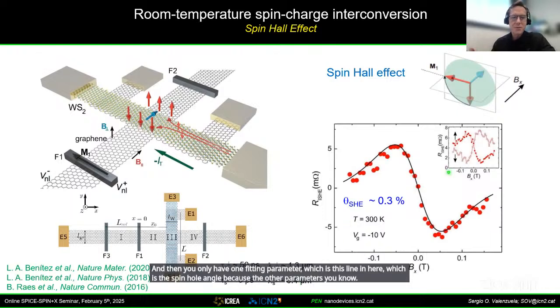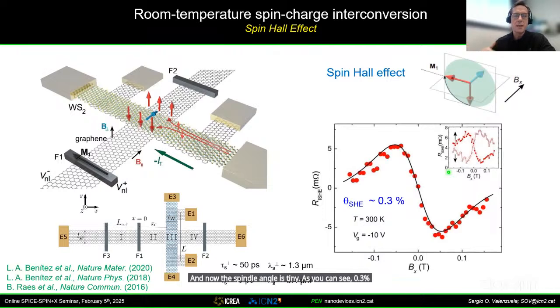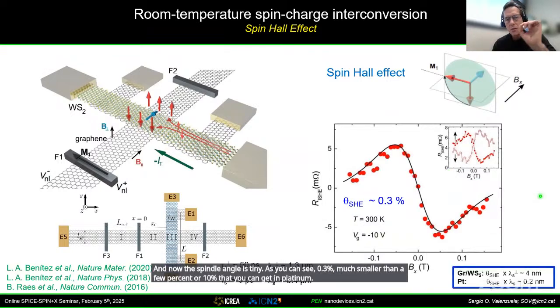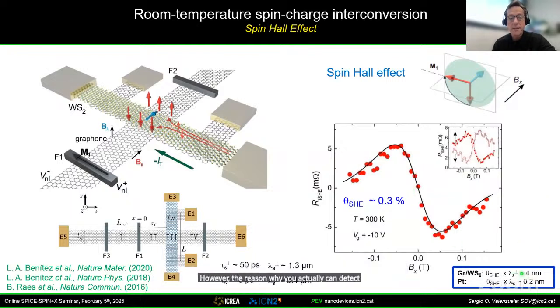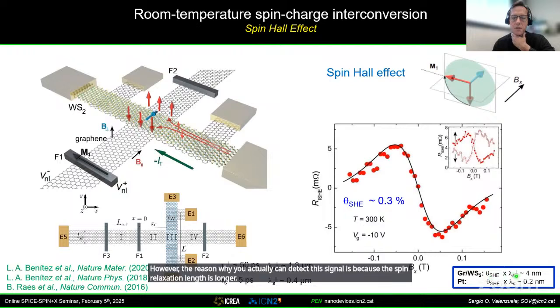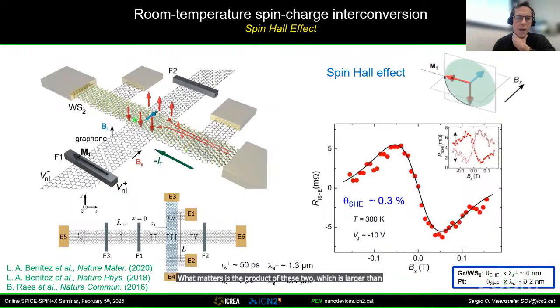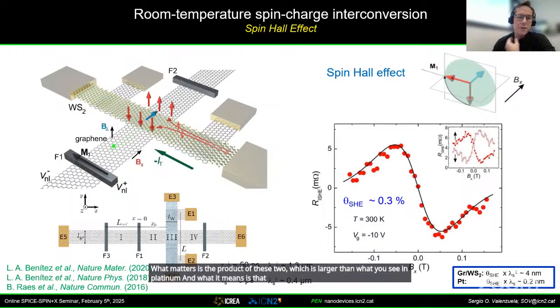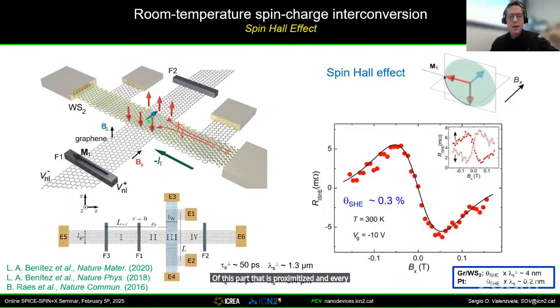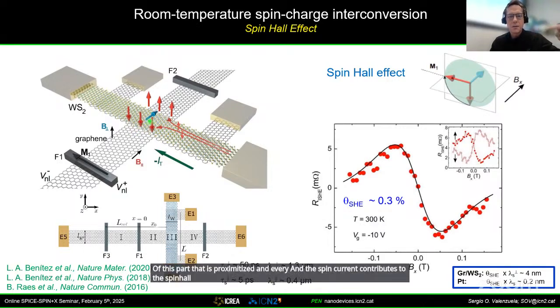And now the spin Hall angle is tiny, as you can see, 0.3%, much smaller than the few percent, or 10%, that you can get in platinum. However, the reason why you actually can detect this signal is because the spin relaxation length is longer. What matters is the product of these two, which is larger than what you see in platinum. And what it means is that in the inverse spin Hall effect, you have a spin current, the spin current propagates over the whole length of this part that is proximitized, and the spin current contributes to the inverse spin Hall effect signal along the whole width. If you had a much shorter spin relaxation length, you would have a shunting that would be much more important, and then you would not see it.